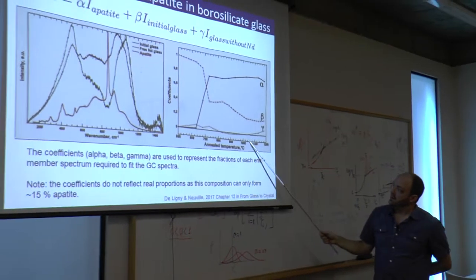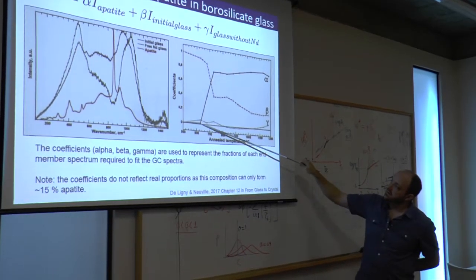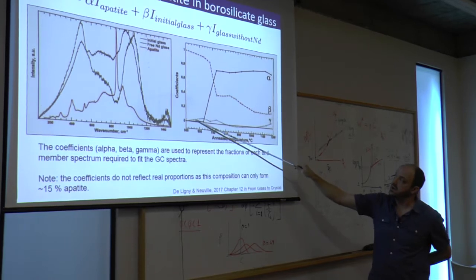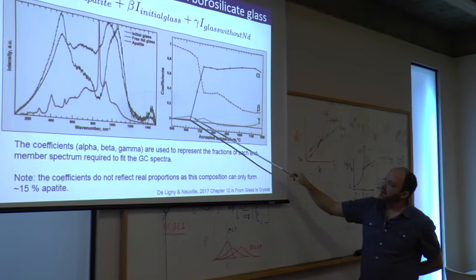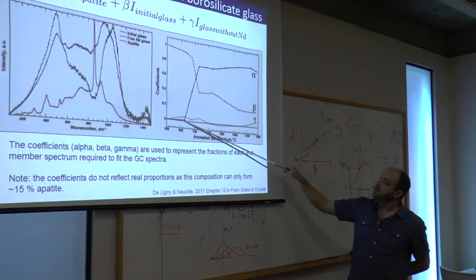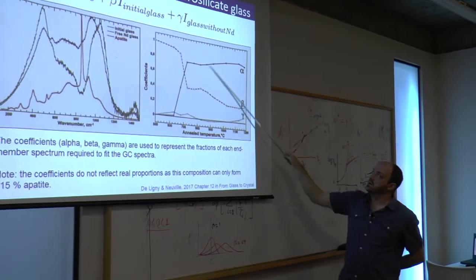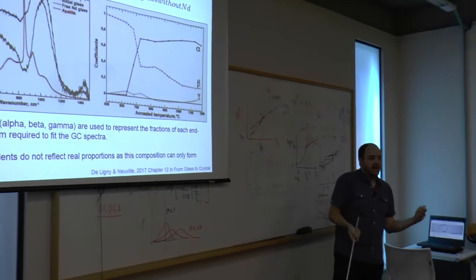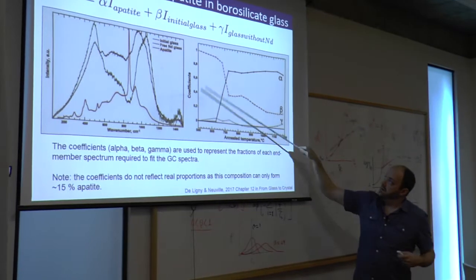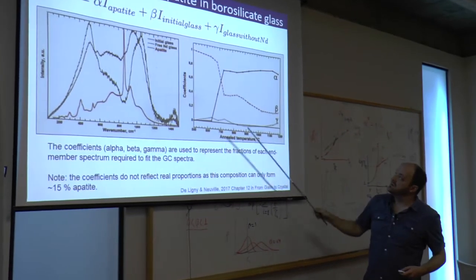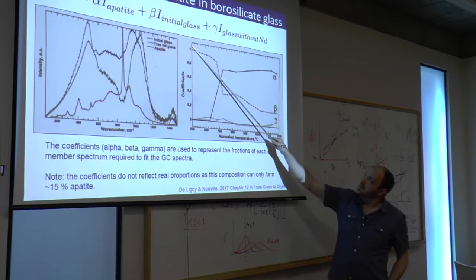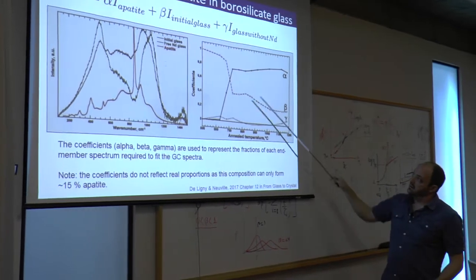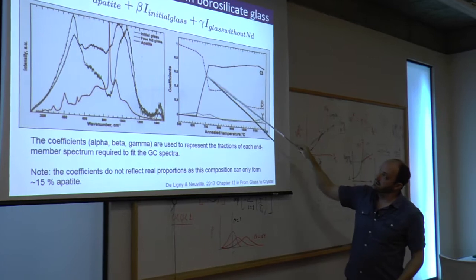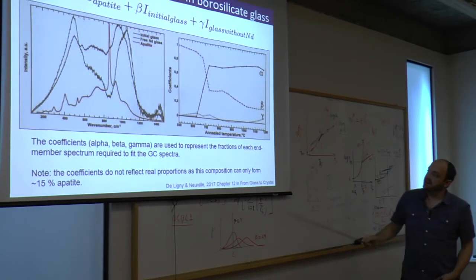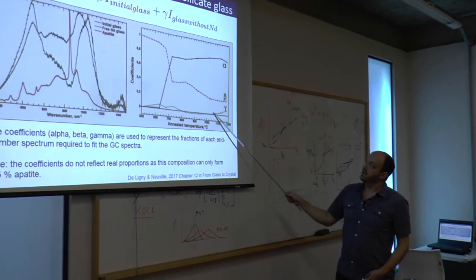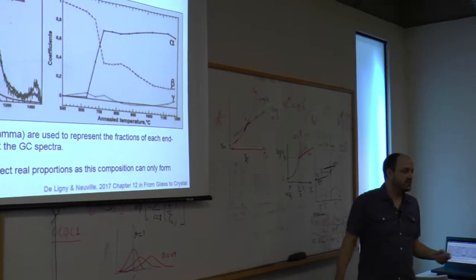As you have increasing annealing time, for short times at low temperatures, you get almost no apatite formation, so this isn't good. But as you hit above 640 here, you get a really large signal from the apatite. And this is quite large as a result of this difference in scattering between the mineral and the glass phase. On the opposite side, what they wanted is the glass without neodymium, so this gamma. And what they showed is that, yes, the initial glass with neodymium does reduce its intensity, its proportion of the spectra does drop as you get the crystallization of the apatite, but you still get only a small amount of glass without neodymium. So it kind of didn't work, but it's a good idea.